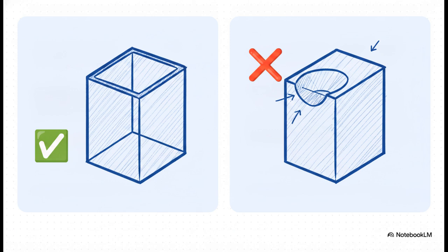Thick sections of plastic cool a lot more slowly than thin sections. So as that thick puddle of molten plastic cools down, it contracts. If the thinner walls around it have already frozen solid, that contracting thick section actually pulls the exterior surface inward. That's what gives you those ugly craters we call sink marks. Or even worse, it warps the entire part because of internal stress. So the golden rule here: you never want adjacent walls to differ in thickness by more than 25%.